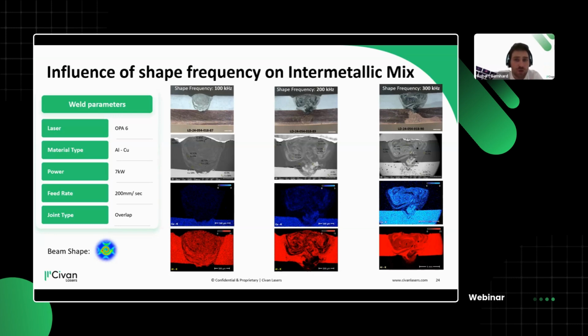With a different parameter set, this would also be true for coated materials, where you might want to handle aluminum-silicon coated steel plates and dilute the coating into the base material, so you get rid of it. You don't need to vaporize it. So there's a way of saving process steps at the same time.